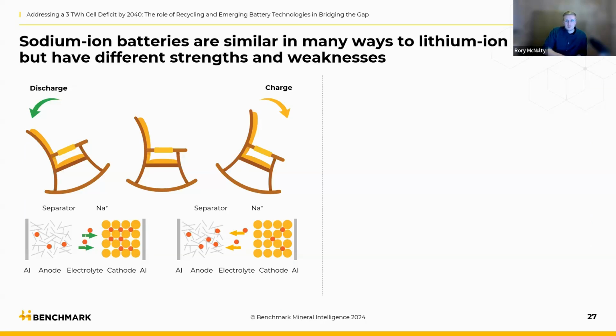So quickly focusing in on the sodium-ion battery first, the ability to alleviate some of that supply stress on the lithium-ion battery. Sodium-ion batteries and lithium-ion batteries are very similar in the way that they operate. They both operate by this rocking chair mechanism. What happens is that the alkali metal ions, be it sodium or lithium, are stored within a metal-based cathode. Upon the charge cycle, those ions are physically removed from that cathode structure. They migrate through the electrolyte and they're inserted or intercalated into a carbonaceous anode. The only difference really between the lithium-ion battery and the sodium-ion battery is the ion that's used to carry that charge. Energy is then passed around your system, given the potential difference between your cathode and your anode material.